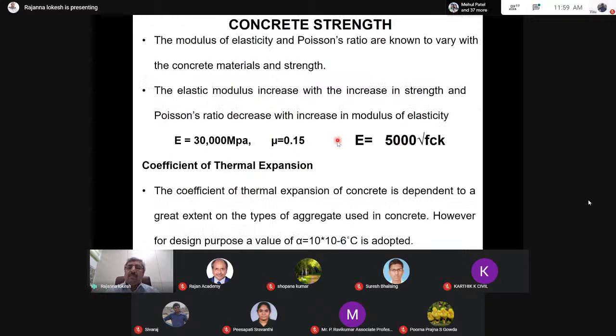The important parameters that also count are the material properties of concrete, that is, the elastic modulus as well as Poisson's ratio. As the elastic modulus increases, the Poisson's ratio decreases. Elastic modulus is a parameter which is dependent on the grade of concrete. If PQC of M40 is used, the E value can be 30,000 MPa. If the grade of concrete varies, it can be calculated using the equation 5000 root FCK.